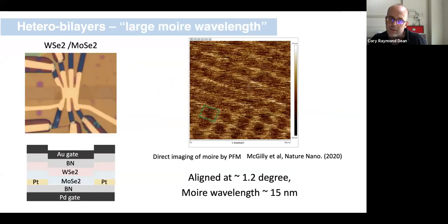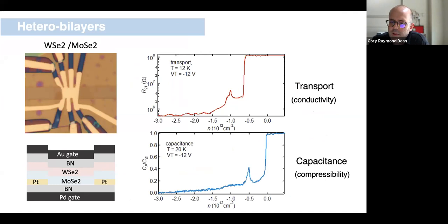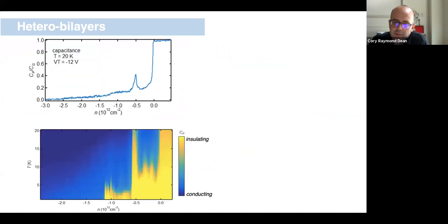So here we're studying transport in a twisted WSe2, MoSe2 system. This particular device is twisted to 1.2 degrees with a Moiré wavelength of about 15 nanometers. All I want to highlight here, and I'll skim the details a little bit, is that if we cool the system down, what I'm plotting here is a capacitance measurement. Yellow basically means it's insulating, blue means it's not insulating. As we cool the system down, what we see is that the half band insulator emerges quite strongly.